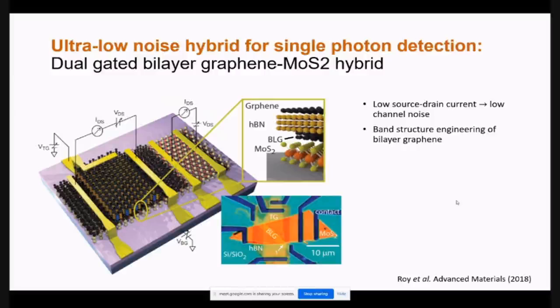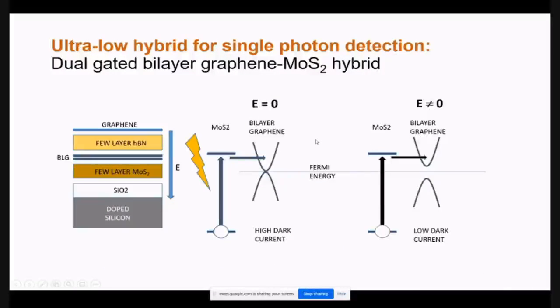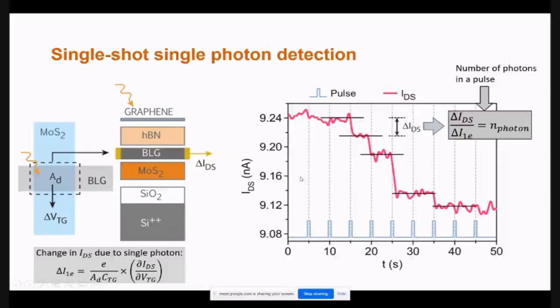And we made a device like this with bilayer graphene, because in bilayer graphene you can apply an electric field from the top, and you can open the band gap, the way I showed you in the beginning. So if the band gap opens up, then the dark current goes down, and we will be able to make an extremely low noise photodetector. And this is indeed what Kollol and others, Tanveer and others did. You can see for every pulse of light, there is a change in current in this heterostructure, where graphene acts as a top gate and a window through which light comes and hits the molybdenum disulfide layer underneath. Then the electron goes into the bilayer graphene, and you get the photoresponse.